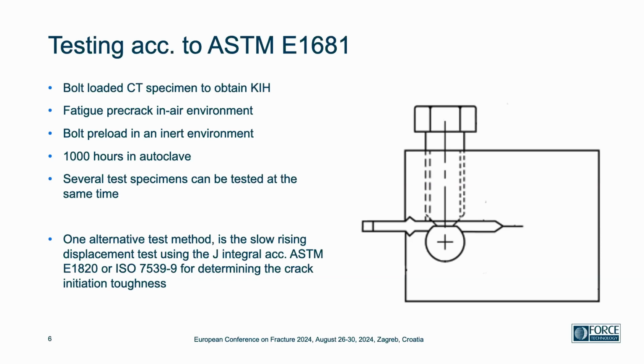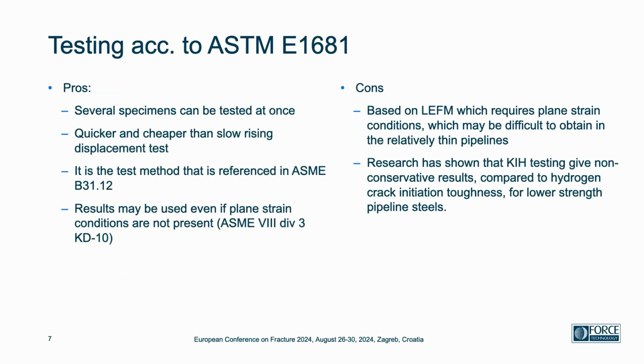One of the alternative test methods that we have also been discussing, and also recently, is the slow rising displacement test using the J integral according to ASTM E1820 or ISO 7539-9 for determining the crack initiation toughness. And when we are looking at these two different methods, as I said before, one of the pros for the compact bolt-loaded test specimens is that you can test several specimens at once. It's quite cheap compared to the slow rising displacement, as you can only test one test specimen at a time. It is the test method that is referenced in the ASME B31.12 and all the way through the other standards.